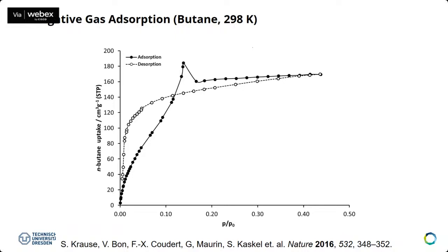Now you may say, okay, 111 Kelvin, that's exotic. Who cares? I mean, that's not for applications. I will show you that this also happens at room temperature. You can do this experiment in your lab with butane gas, so camping gas in the end. And my student Simon Krause at that time had the idea to film the sample and to check what is going on when you approach this very strange negative gas adsorption step.